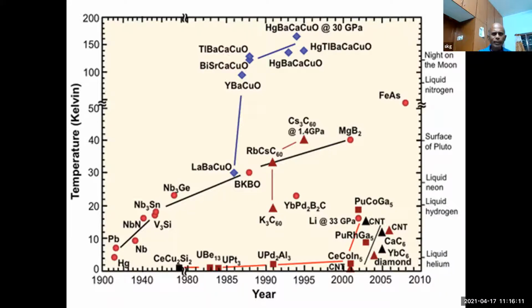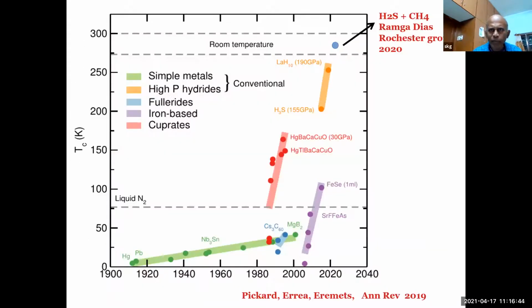So it seemed to have saturated there, but there are good signals that if you massage cuprates, it could go even higher. There are competing instabilities which often bring down the transition temperatures. I will come to it later. So in this picture, you see there are many attempts to make new superconductors. One of the simplest and most surprising superconductors is MgB2. It was on the shelf of many people, and Akimitsu found superconductivity with a Tc of nearly 40 Kelvin, and then more recently iron arsenide superconductors.